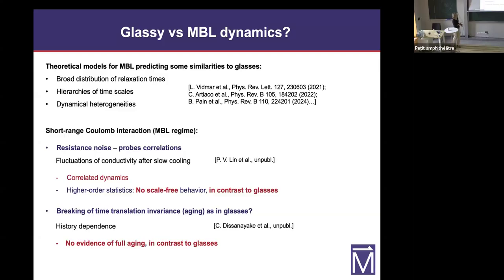And also more recently, this is still actually ongoing, we wanted to see whether MBL exhibits a breaking of time translation invariance like glasses do. So what does this mean? What's the aging or breaking of this time translation invariance? It means that the properties of the system depend not only on the time when you measure them, but also on how the system was prepared, on its age. For example, in the glass case, if it's older, it's slower, and so on. So we checked for that. So far, we have not seen evidence for the so-called full aging, but as I said, this is still ongoing.